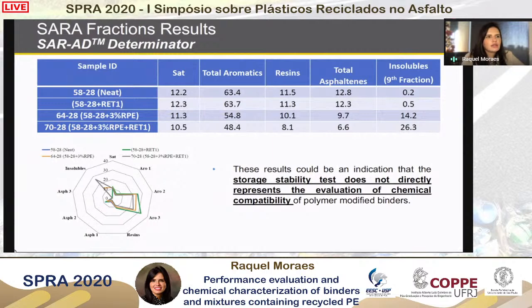But one thing that is important for us to see from these results is that they could be used as an indication that the storage stability test alone does not directly represent the evaluation of the chemical compatibility of the polymer modified binders. You remember that these samples were selected after initial screening with the storage stability test using the softening point, where we see that the binders passed the initial screening in accordance with the Georgia DOT specification. But when we come to a more detailed or more intrinsic evaluation of the material, we can see that the test does not cover everything, as we can see here from the amount of insoluble materials that we have in the blends with the recycled plastics.